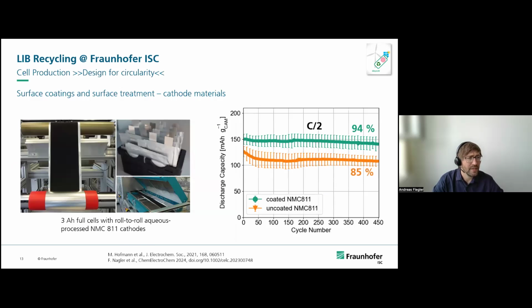This we incorporated in the electrodes and processed NMC 811 cathodes via roll-to-roll process and built pouch cells with a capacity of 3 amp hours and measured them over 450 cycles, and we see that with this phosphate coating, we can increase the discharge capacity by around 10%.